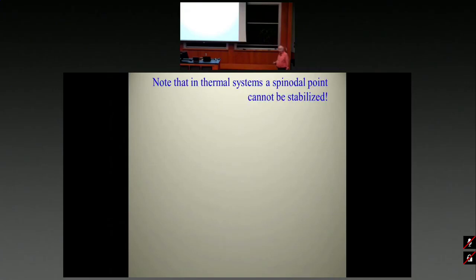And now I just want to finish with a short comment that all this is working so nicely because the temperature is 0. What I'm trying to say, you see, spinodal criticality is known for a long time. Everybody knows that near the spinodal, the free energy has a flat region with respect to, in the derivative with respect to order parameter. No one has ever seen a spinodal criticality. And the reason is that when you have temperature, it always jumps before you go to the spinodal. You have the Maxwell construction. Here we are at temperature 0. So temperature 0 allows us to stabilize a spinodal that is very difficult to see otherwise.